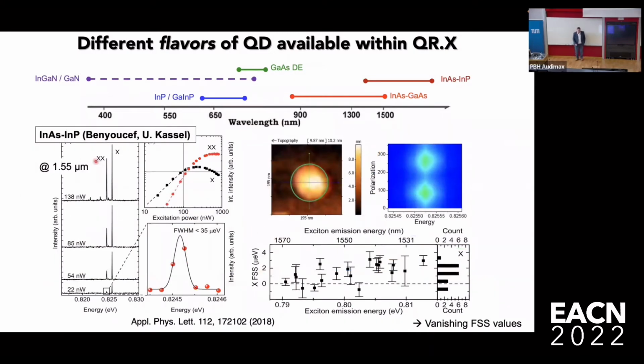If you want to go to longer wavelengths, you have to go to different material systems, like the indium arsenide, indium phosphide material system. For quantum repeaters, that's very important. We can now go to 1.55 microns with these quantum dots. And this might sound unremarkable if you're not from the field, but getting high quality, Fourier limited quantum dots, which are good for quantum optics experiments at this wavelength, is quite a recent development. It can now be done.